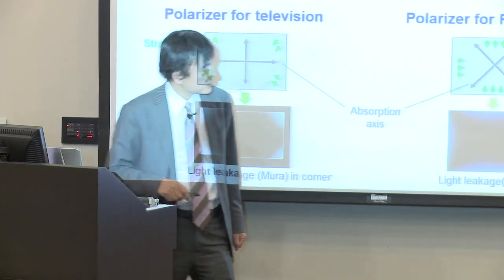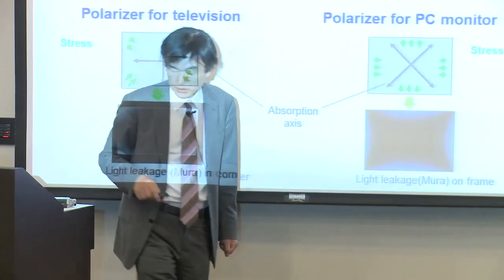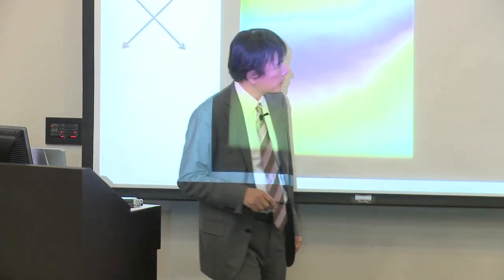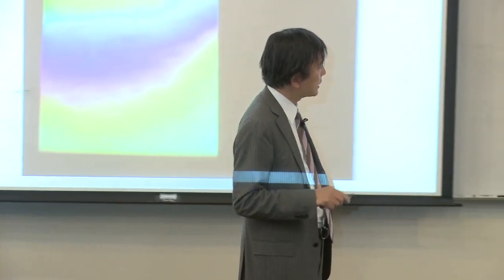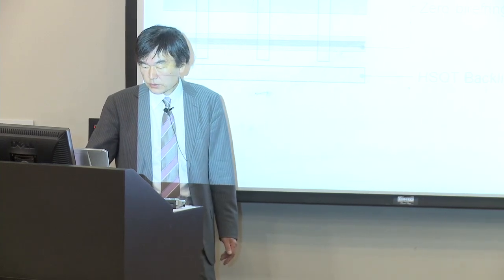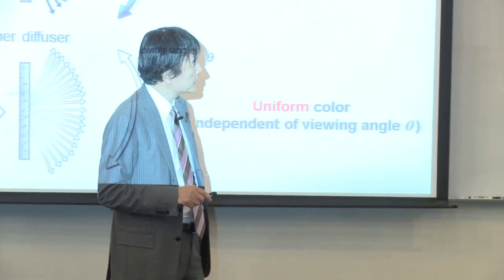And as for the zero birefringence films, these are the leakage of the light due to the birefringence of the polymer films. So if the polymer films are extruded, usually birefringence is very serious. But with using the zero birefringence polymer, even by extrusion process, the birefringence is really zero. As for the diffuser, usually the problem we have to consider is the color uniformity by changing the viewing angle.